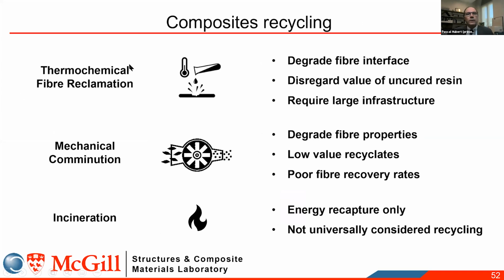First, you can use thermochemical fiber recycling so that you can reclaim the fibers out of the composite. That can be done at an end-of-life stage or with manufacturing scrap. What you do is basically get rid of the resin. This often creates some issues with the fibers. You degrade the fibers a little bit, and you just throw away the resin, which is in some state uncured if you take manufacturing scrap. And you often have to have large infrastructure to do this.